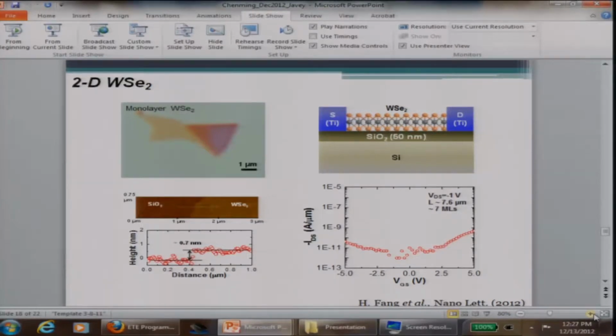And one of the materials that we looked at was tungsten diselenide. You can make devices out of monolayers of tungsten diselenide. People had looked at it before. They made devices, and we made devices also. And this is what people observed and published before, and that's what we initially observed as well.